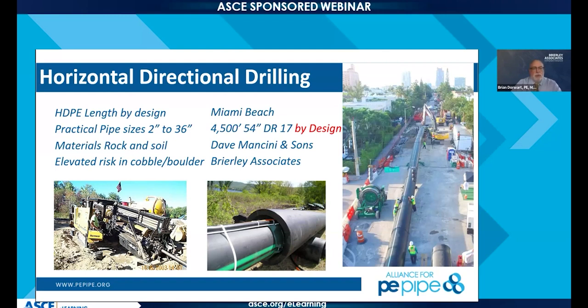The nice thing about the HDPE, we're going through granular material, really nasty, cobbly boulder. The only material that we really determined was going to be tough enough was HDPE. That kind of material can break PVC, and it'll gouge any surface and corrosion protection you have on steel. HDPE is the ideal component. We fused it all together, pulled it back in one shot in about 3 hours. It shows that in bad conditions, toughness really does make a difference.